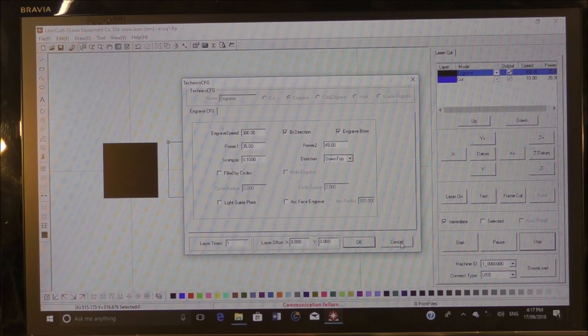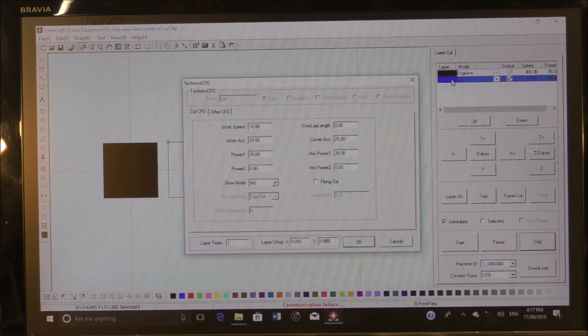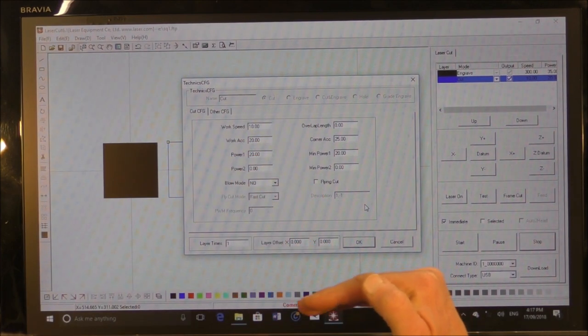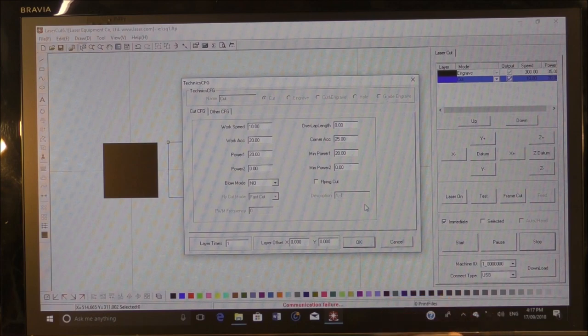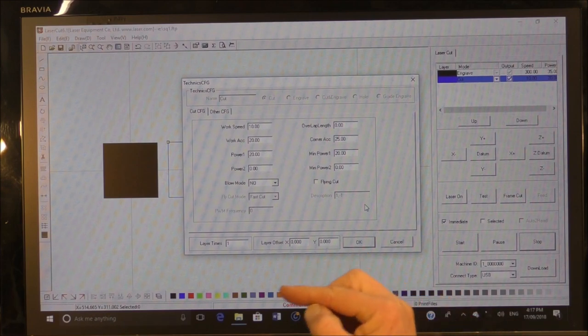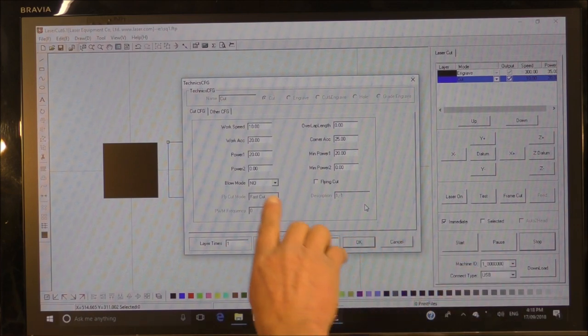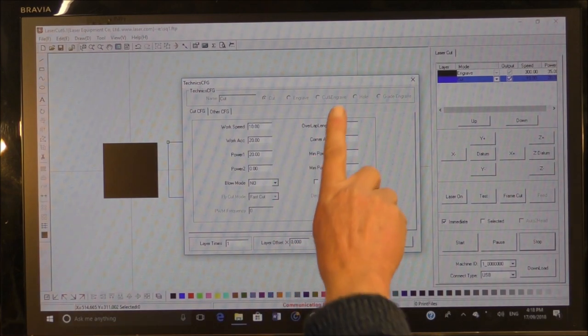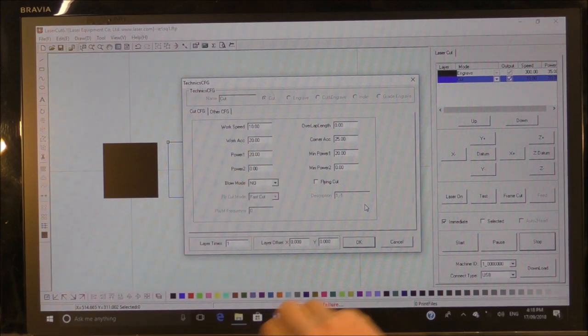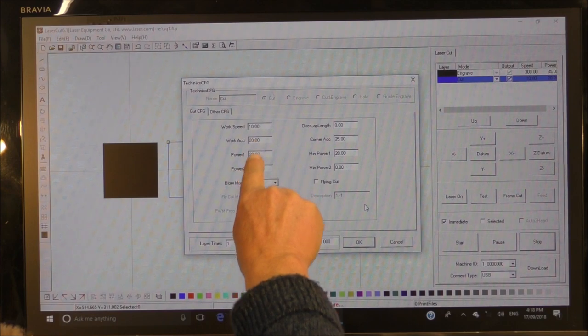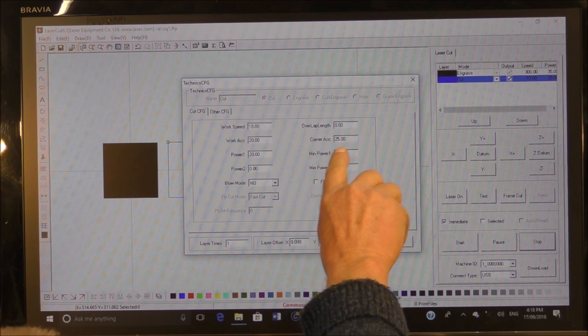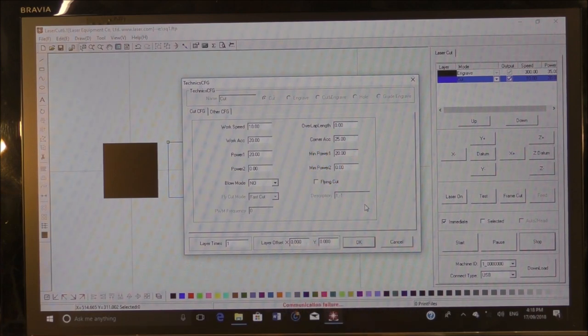Now then, that's okay, that's been done. I've already calculated that one. Now the cut layer - it's running at 10 millimeters a second, so it's running very slow. I don't actually want to cut through the glass, what I want to actually do is mark the glass with a very fine line. Hence the power level is 20 percent and 25. This is strike of the arc as it were, and this is in the corner, so this is the immediate fire up of the laser. We don't want to cut through - this is the corner power. So I think that's fairly self-explanatory.